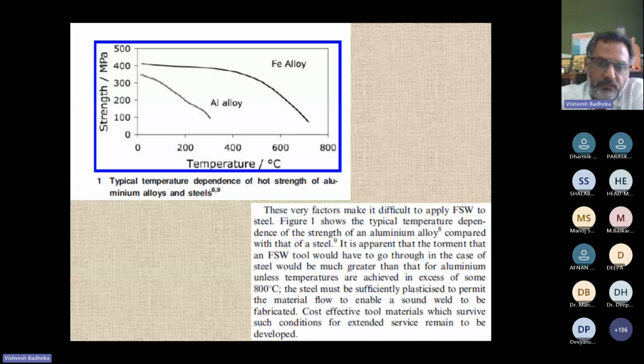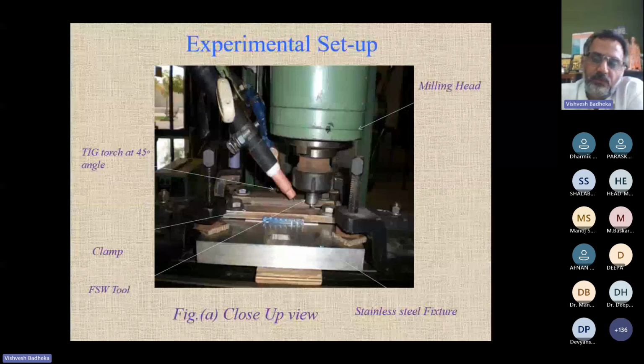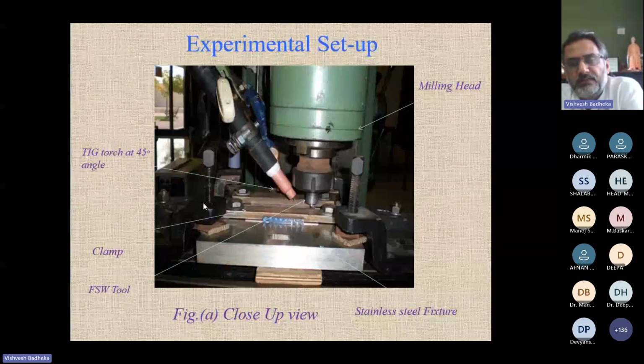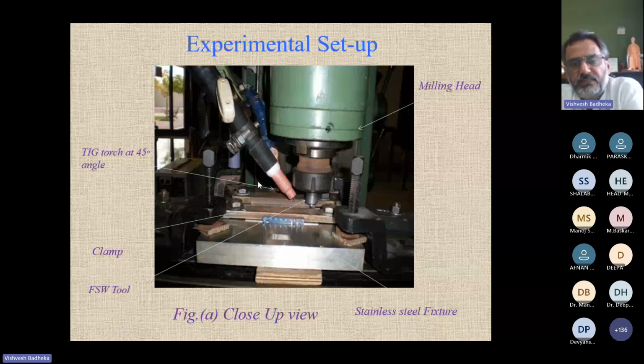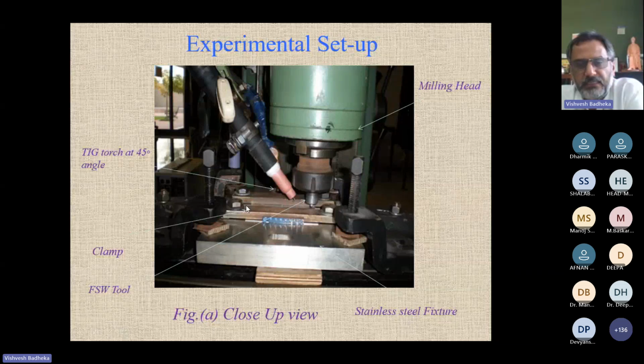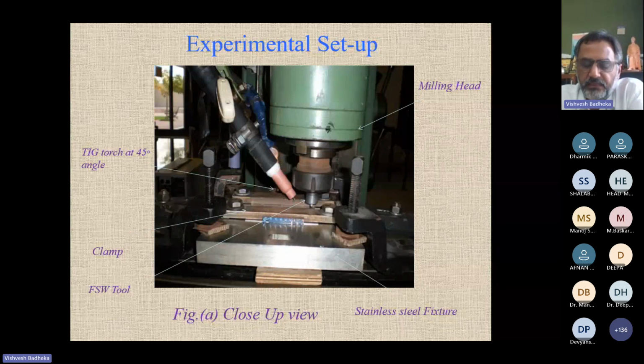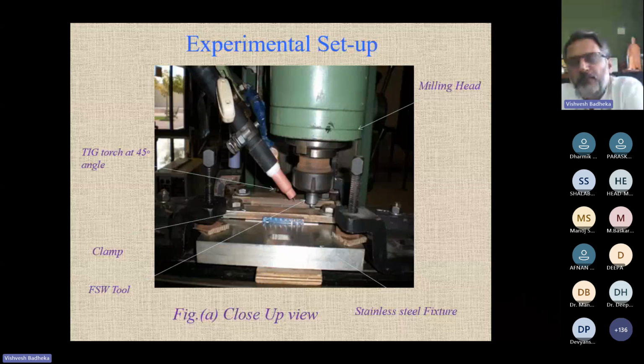So that's how friction stir welding of steels and other high temperature materials is more challenging compared to aluminum. Fine. So in our laboratory also, we have done such a development, friction stir welding with assisted heating with the help of a gas tungsten arc welding torch. You can see here, there is a gas tungsten arc welding torch which has been put ahead of the tool, and please understand, the purpose of this preheating is not to melt the material. The purpose is to do the preheating. So this preheating will help you to reduce the wear of the tool and the load on the tool, right?